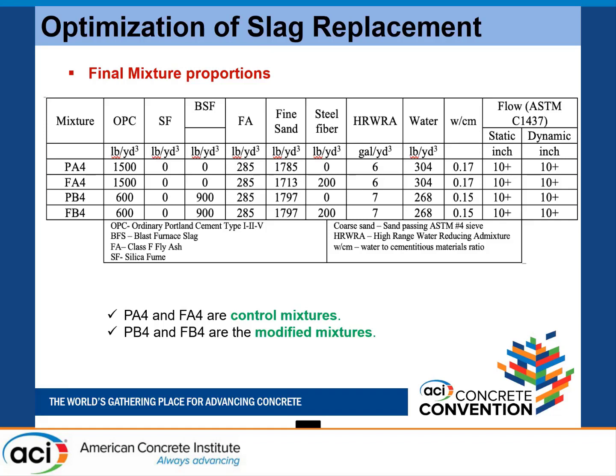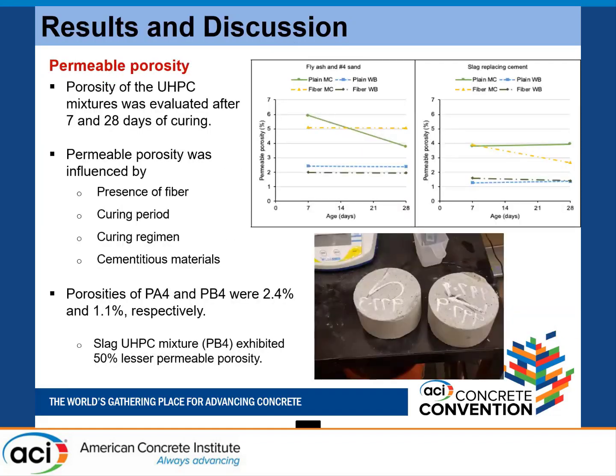But we had a lot of cost savings and environmental impact reduction by using 60% slag, because UHPC is a very high cement factor composition. Then we measured permeable porosity. The porosity is drastically reduced using slag. In the control mixes, where there is no slag, the permeable porosity of UHPC is 2.4%, while in the slag mixes, the B series mixes, the permeable porosity is just 1.1%. That means the presence of slag reduced the permeable porosity by 50%, which is a great thing for any concrete, basically.